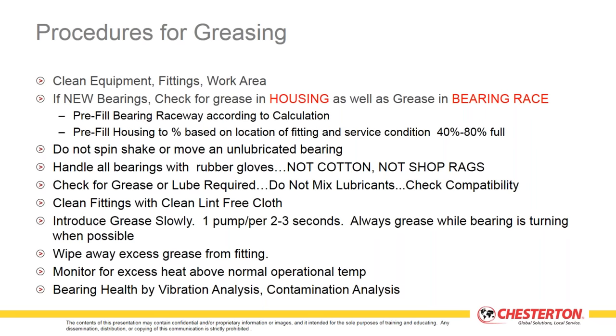Introduce the lubricant slowly. In terms of grease, one pump or one stroke of the grease gun every 2 to 3 seconds. The electric guns that put in up to 6 to 7 times the amount of grease in seconds are prone to overpressurize the bearing, distort the bearing, and cause damage to the bearing. Introduce the grease slowly. And typically, always while the bearing is turning, to redistribute that grease around the entire circumference and not just trap it in the top of the housing. Always wipe off any excess grease from the fitting. Don't leave it as a mess to collect dust and dirt.